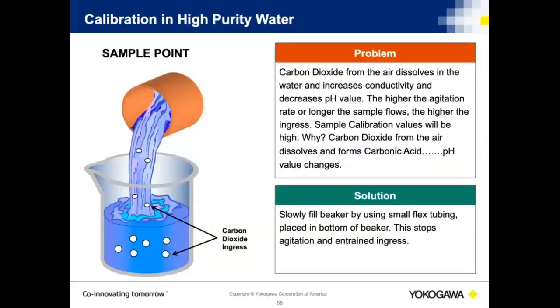High purity water. If we do a grab sample comparison, what we want to do is make the measurement at the point where the sample is coming out of the sample system. In other words, directly into the sample trays. You take a beaker, put an overflow or flexible tube into the bottom of it, and flow the sample into the beaker and let it overflow. You then make your measurement directly inside of that beaker.